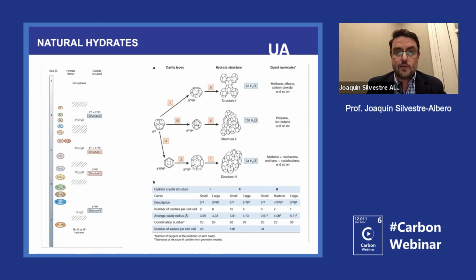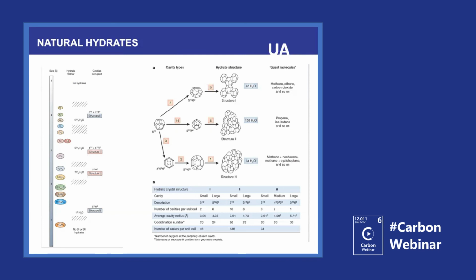No? Because what we are facing, we were working with MOFs and with zeolites. So in all these materials, it's very easy to have a preferential interaction of the water with the walls. And then when you put the methane, the system doesn't want to make the hydrates. No? And that's why carbon has the perfect chemical surface to promote the interaction of water with methane. And this is very important. But as I say, we never tried with alcohols or other systems.